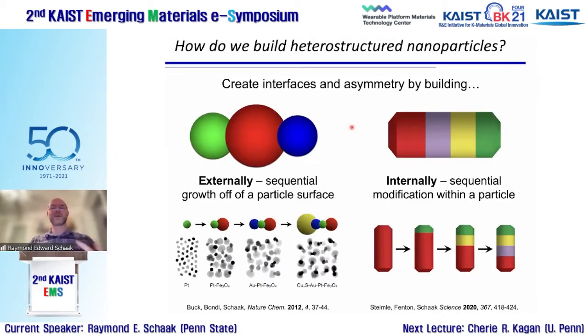And there are increasing numbers of ways that researchers around the world have begun to approach these synthetic problems. I'm going to show you just two of the ways that my group has approached these, and our focus in everything I'll talk about in the next bit of time is creating interfaces between materials in a single nanoparticle, in a way that's asymmetric. We do that in two different ways. One is to create interfaces and asymmetry externally by starting with a seed nanoparticle like platinum, and then growing other nanoparticles off of it, a seeded growth type reaction.